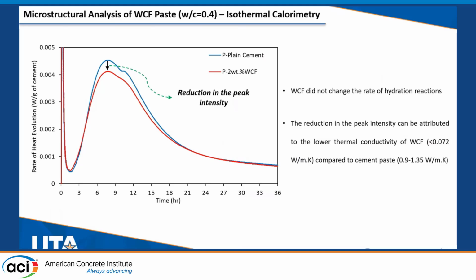Following our experiments, I used isothermal calorimetry to determine the rate of heat evolution of hydration reactions for both plain cement and WCF paste. As you can see, a similar rate of hydration reactions is observed for both mixes, but the WCF could reduce the peak intensity of heat evolution due to the lower thermal conductivity of these fibers that reduces the heat flow of the material.